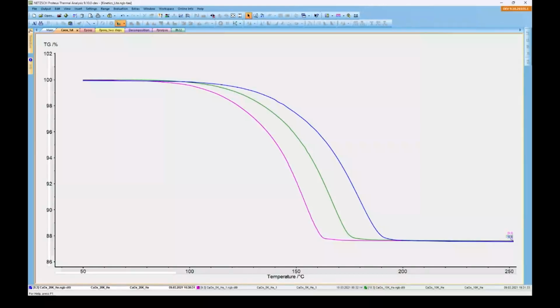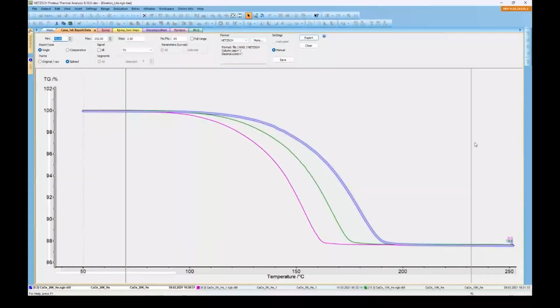So up to now, it was necessary to take each curve. After that, you should export this curve to a file. You should select the evaluation range. You must check all fields, if it's TG, if it's spline or original. You must set a number of points for export. It should not be too few points, because then it's not enough for good analysis, and it must not be a big value. For example, it could be 500 points.